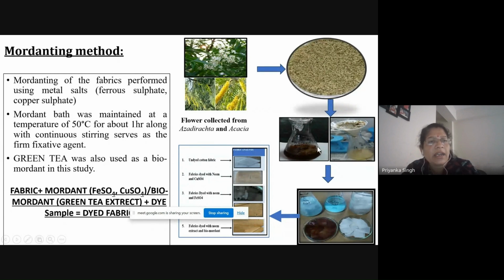Then we added a specific type of mordant. We used two categories of mordant. In the first category, we took metal salts, mainly ferrous sulphate and copper sulphate. And as a natural biomordant, we used green tea. So how did we do the mordanting? First, we treated the fabrics with a specific dye. After that, we added the mordant and then incubated the fabrics at 50 degrees Celsius for 1 hour. After that, we observed the color variation in the cotton fabrics compared to the plain fabrics.